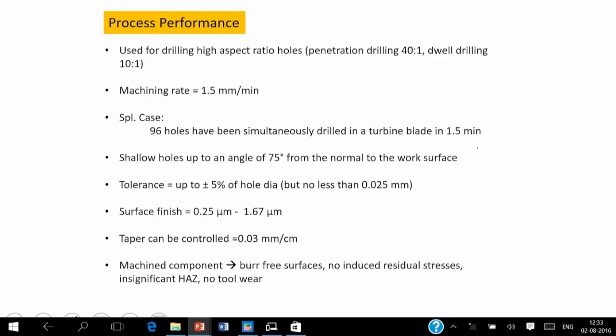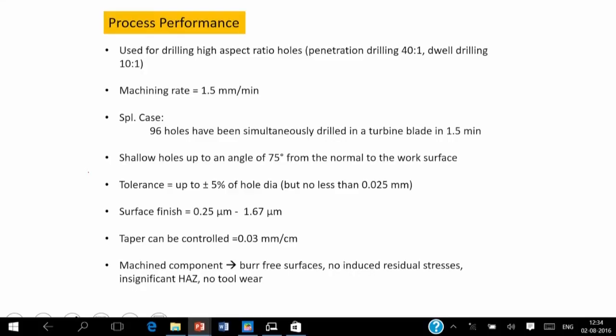Process performance: it is used for drilling high aspect ratio holes. For penetration drilling the length to diameter ratio of the holes is 40:1, and for dwell drilling it is 10:1. Machining rate is 1.5 millimeter per minute. In a special case, 96 holes have been simultaneously drilled in a turbine blade in 1.5 minute. Shallow holes up to an angle of 75 degree from the normal to the workpiece can be made. Tolerance is up to plus minus 5% of the diameter of the hole to be machined, but it should be no less than 0.025 millimeter. Surface finish achieved is 0.25 micron to 1.67 micron.